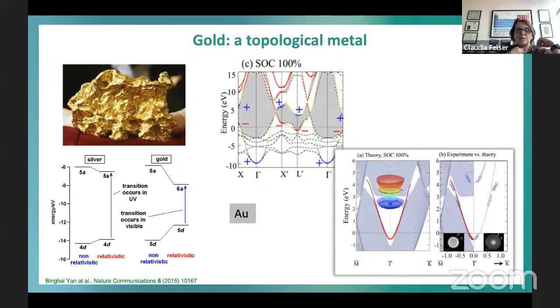And this is the reason why we like gold much more than silver, because it has a much nicer color. So I like gold very much, more than silver. This is exactly—if you see the band structure of gold, this was a nice project with Bin Hai—you see here the s band overlap and the d band overlap. This is the real band structure of gold, and you see that you have also here this band inversion.